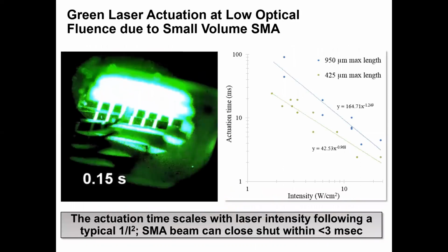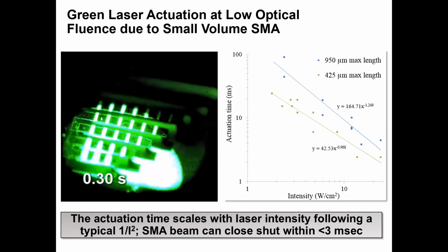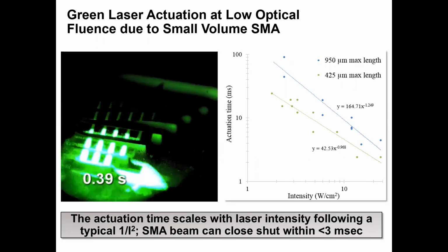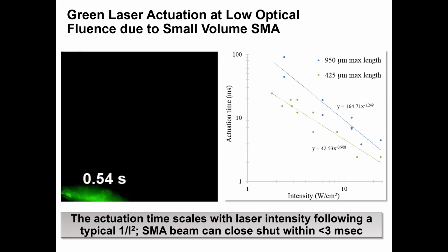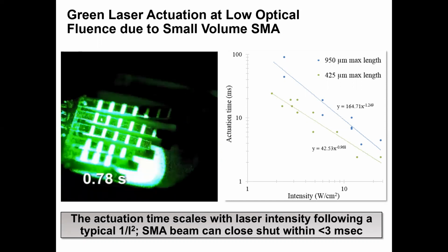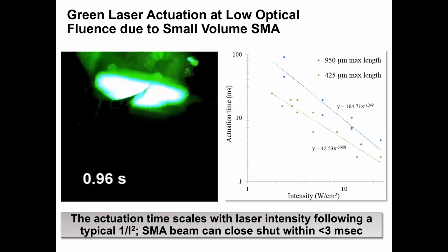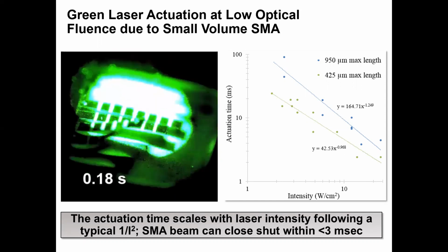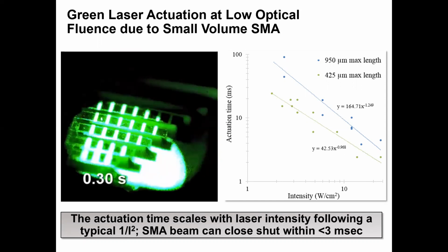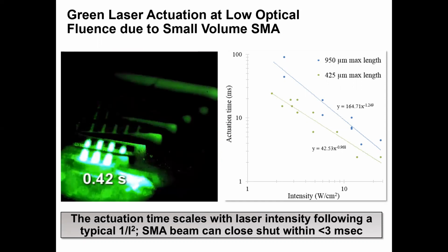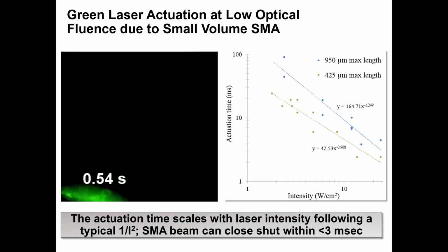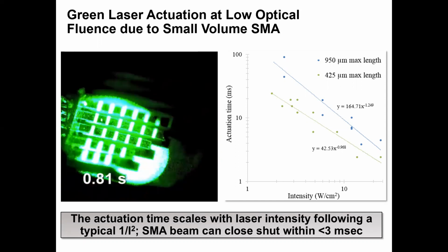So here it was demonstrated that the green laser could supply enough heat energy to actuate the NiTi SMA MEMS in a rapid fashion. The actuation followed a 1/I² trend, where I is the laser intensity. And the actuation time was shown to vary between about 100 milliseconds at lower fluences on the order of 1 to 2 watts per centimeter squared, and it could happen as quickly as a few milliseconds if the optical fluence was 10 watts per centimeter squared or more.